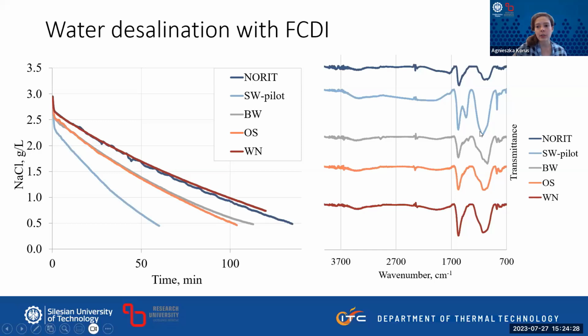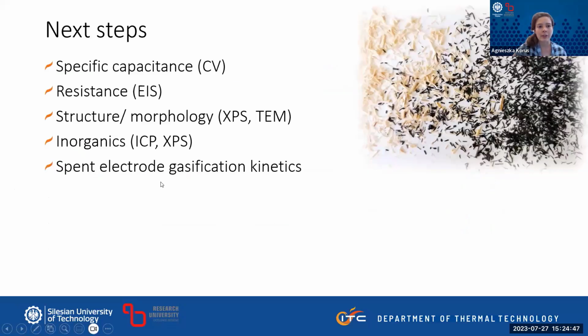This larger peak here is also either oxygen heteroatoms in the structure of the char, or some inorganics such as silica. So we definitely need to dig deeper into the chemistry of these materials. For the next steps, as I mentioned, electrochemistry to see the resistance and the capacitance of the char, and then hopefully some digging into the morphology and chemistry of the chars to see what's behind their performance.